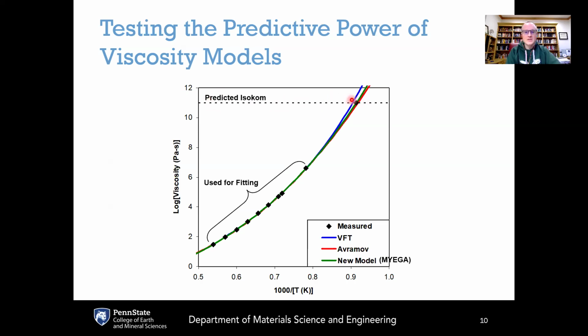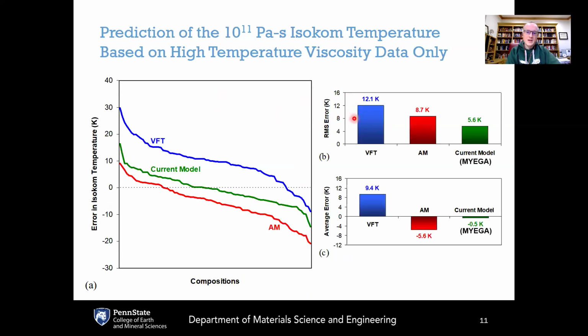the 10 to the 11 Pascal seconds. And what we found is that the VFT equation would systematically overpredict the low temperature viscosities, and it was over-predicting the temperature at that equivalent viscosity by about 12 Kelvin, which is quite a bit. And this is an error that would just get worse and worse the lower that you go in temperatures. Now, the Avramov-Milchev equation was actually under-predicting. So this was under-predicting the low temperature viscosity point by about 5.5 degrees. So it was doing better, but it had systematic error in the opposite direction.